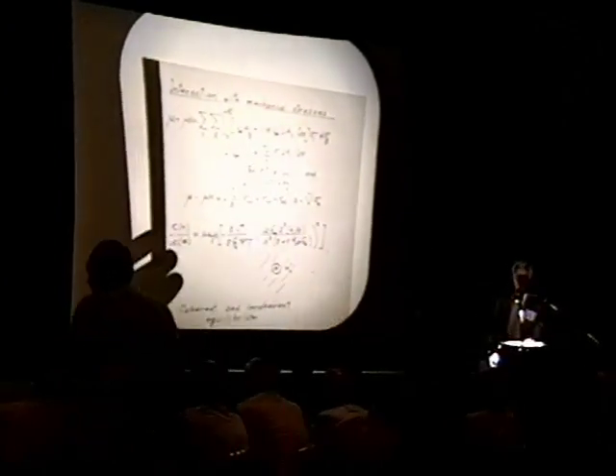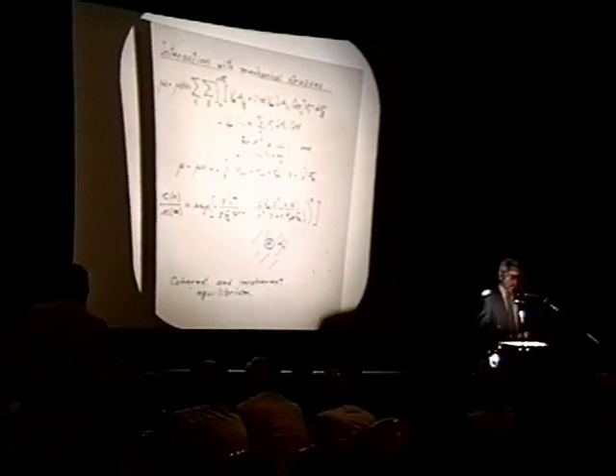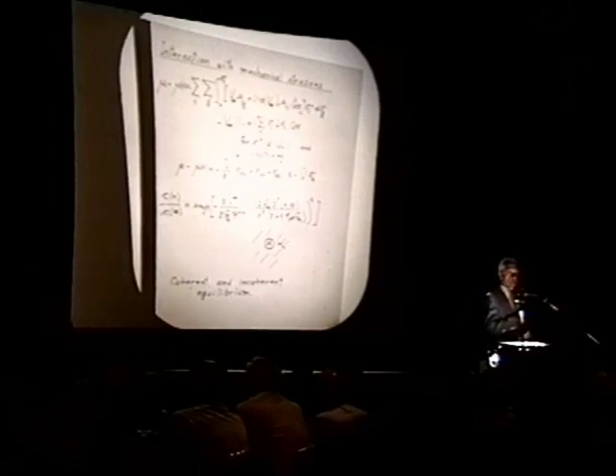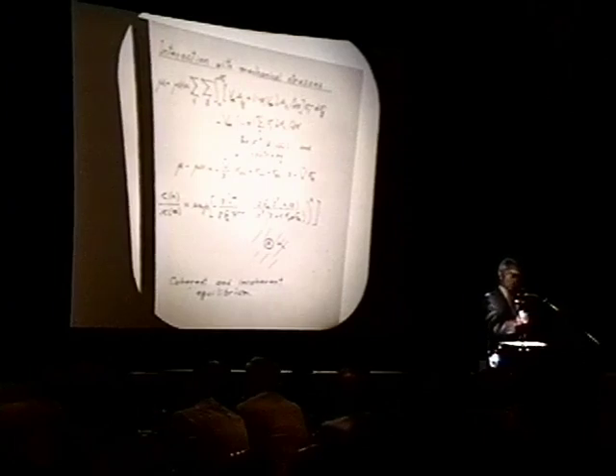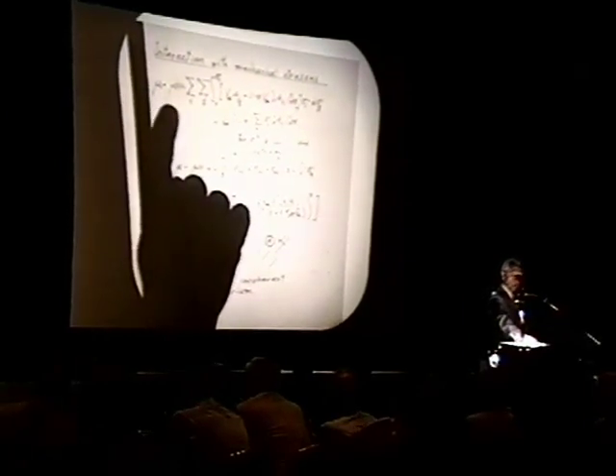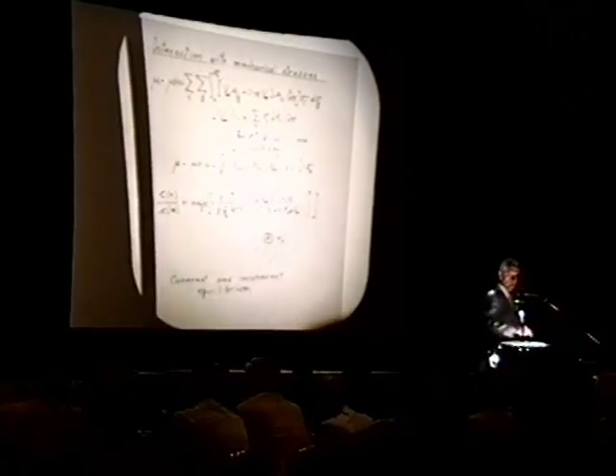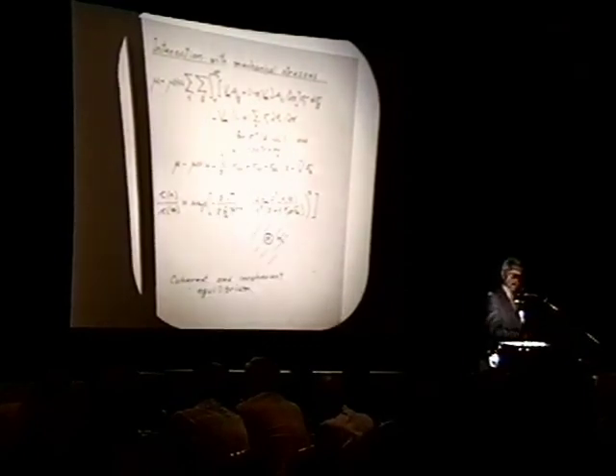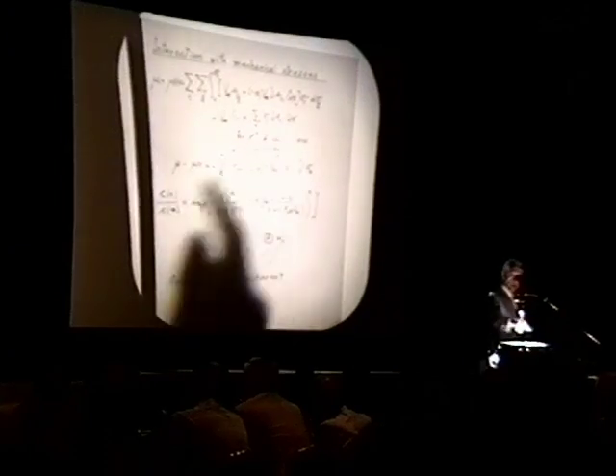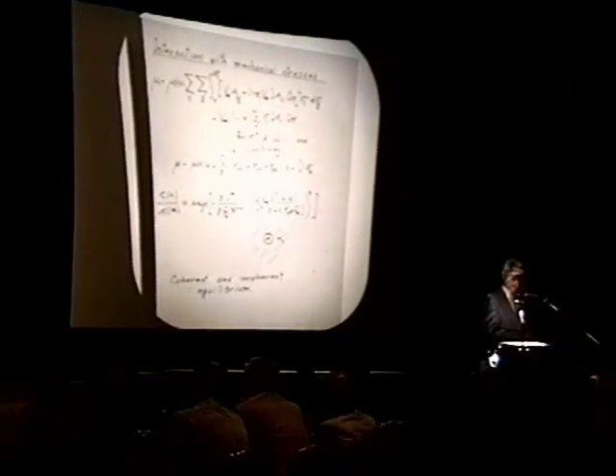Now, I'd like to give you some insight into the effect of mechanical stresses. If you want to compare equal concentrations of dissolved interstitial solutes, of which hydrogen is a prime example today, at the same concentration between a solid which is under mechanical stresses and one which is completely relaxed, with no mechanical stresses, the difference in chemical potential of the dissolved species, or the interstitial, is given by this expression, a sum of many terms, of which Vm is the molar volume of the solution as a whole, Sij are the elastic compliances, X is the composition, the mole fraction of the solute.